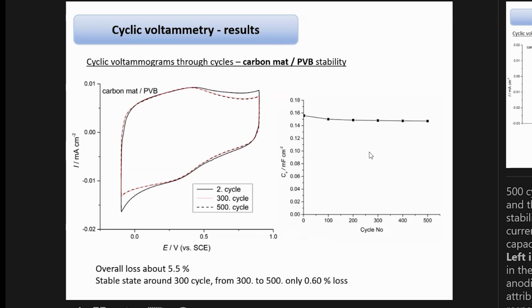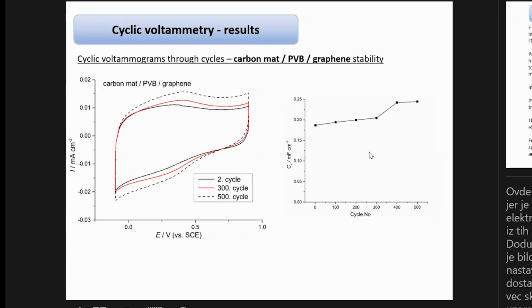in our case. And on the diagram on the right side, we have a diagram showing the actual stability with the increase of the number of cycles. That is, the capacity is very stable over many cycles. Also, on another observed sample that contains graphene, we have similar results, but what is interesting to note, on the right side, is an increase of the capacity, which means that after more and more cycles, the electrolyte is penetrating between some remaining agglomerates of the graphene nanoplatelets in the material.